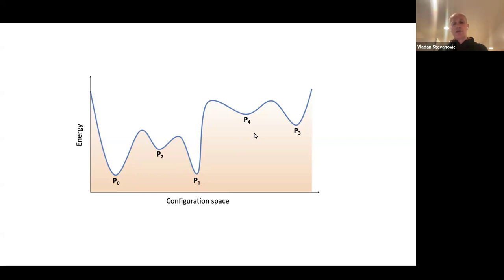So kinetic trapping pretty much means that if you can create some kind of experimental conditions to get your system inside one of the polymorphs that is not the ground state, let's say P1, and if that local minimum is deep enough, then after removing whatever perturbation we applied onto the system to get it into P1, the barrier to go from P1 to P0 will be large enough so that at ambient conditions it will survive, even though it's not the ground state or the minimum of the corresponding thermodynamic potential. However, while I have no problem with this story being qualitatively correct, in my view it doesn't tell us how we get into P1 and what is the likelihood to get into P1 to begin with.